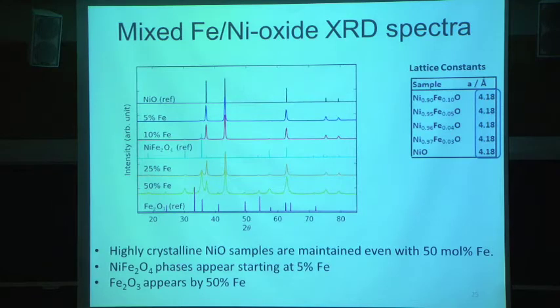Okay, so if we look now, try to characterize what are all of these materials that we're looking at. We start out with our nickel reference, and you see very strong nickel oxide peaks in almost every catalyst as you increase the amount of iron. Here you don't see any real change. There's no shift in the peak positions, right? That's shown over here, that the peak position or the lattice constant you calculate for nickel oxide doesn't change. It's independent of the amount of iron. That suggests that we are not incorporating iron into the nickel oxide lattice at all.